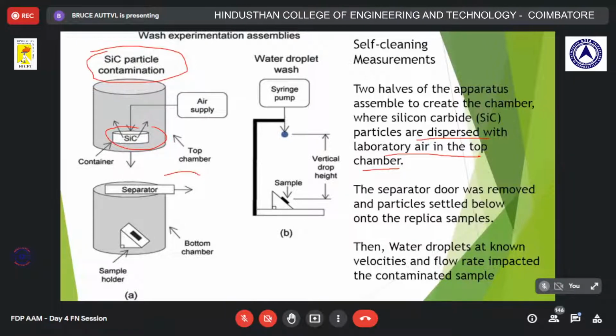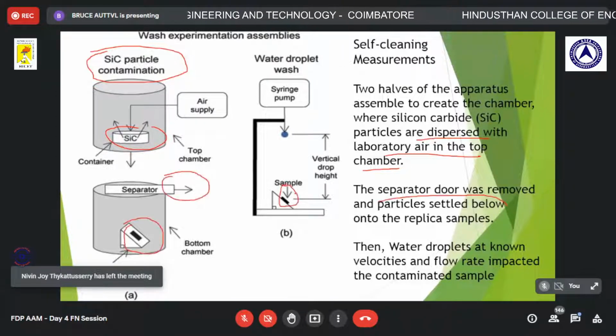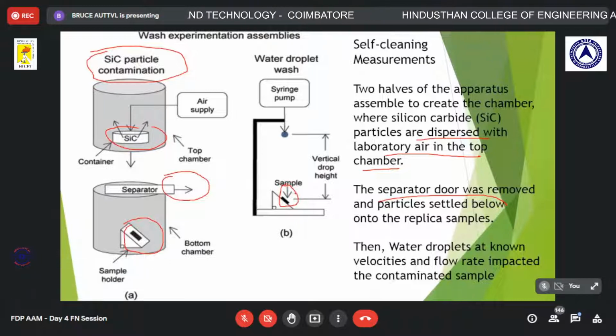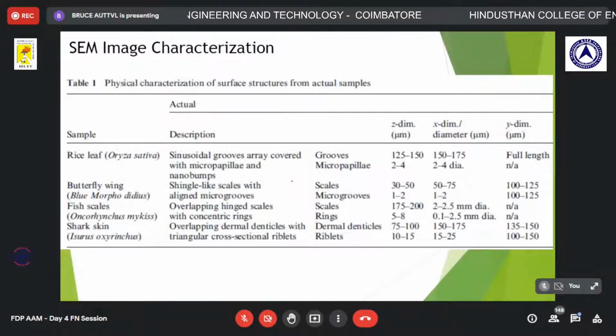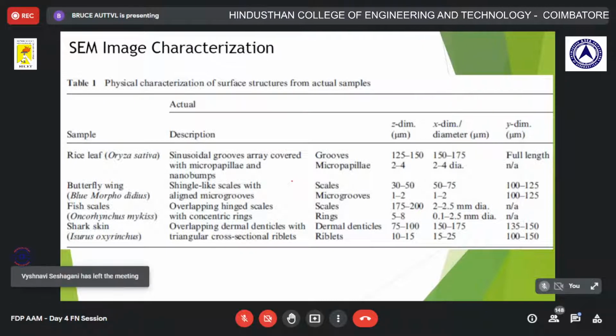And once water droplets at known velocities, with a known flow rate, are impacted on the contaminated sample, you can observe how the replica sample exhibits the self-cleaning characteristics. You can study that. It is something similar to the corrosion experiment. Okay. Now, the SEM image characterization, whether you prepare the specimen with real bioinspired characteristics or it has some preparation defects. If you are able to characterize it properly, physical characterization of the surface structure from the actual sample is sufficient to ensure the accuracy of the process.